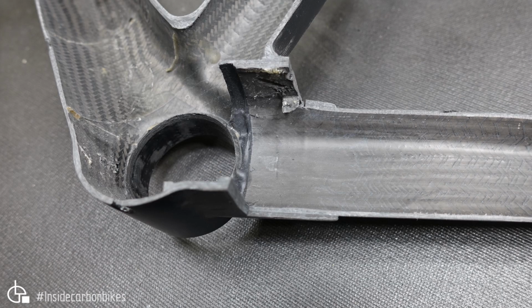And finally, another view of this area. Now, it is a really critical area on the bike, and we do see a lot of problems on bikes in this area, so I'm really emphasizing that. But you get a really nice view of that bond line thickness control through here. You can also see it through there and through there. There's a tiny little void right there, but it is close to the edge. Actually, it's only close to the edge because I cut the section out. So a little void like that, being contained away from the edge, is not that much of a problem at all. I wouldn't be too concerned about that. The other thing you can notice is the different weave pattern.